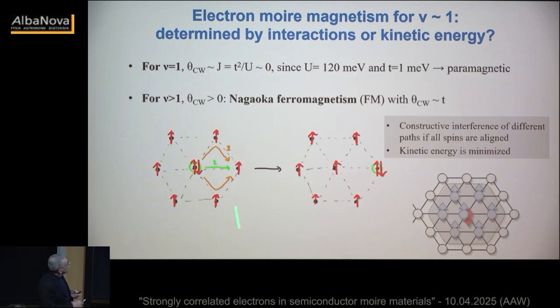Okay? So if nu is larger than 1, however, the physics can be very different. Now, you can actually have a so-called Nagaoka ferromagnetism, proposed about 60 years ago by Nagaoka. And the idea here is this: think about the case when on-site repulsion is very large, so exchange is negligible, and when we introduce extra electrons, of course, we need to provide this extra energy. And then the only relevant energy scale is kinetic energy. So how can this doublon, this doubly occupied site, minimize its energy? It would do so by completely delocalizing over the whole system.